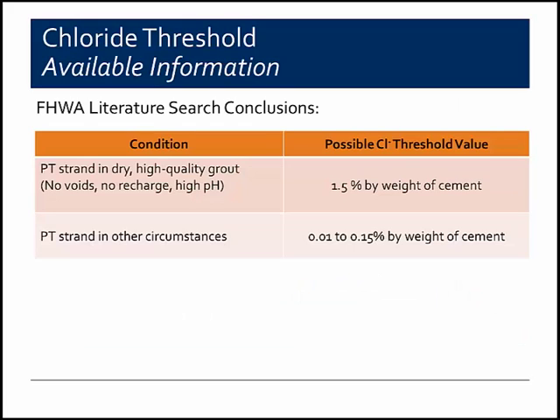So Federal Highway, as a result of their literature research, concluded essentially that strand that's placed in dry and high quality grout, where you have high pH and no chloride issues, no sulfates or anything like that, the chloride threshold may be as high as 1.5% by weight of cement. However, if that's not the case, if you have strand that's certainly in soft grout, or if you do have voids, if there is recharge issues, anything like that, the chloride threshold may be as low as 0.01% by weight of cement.